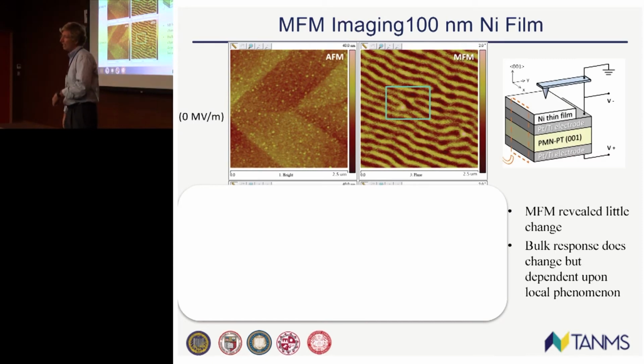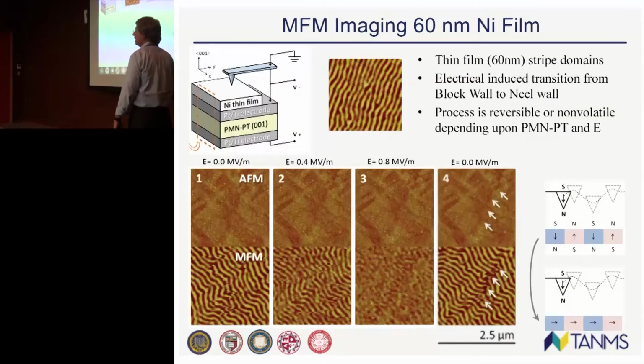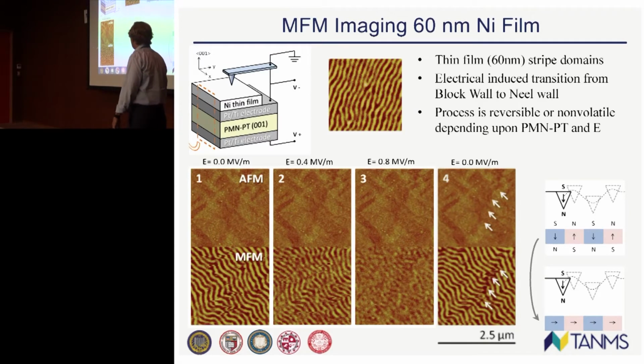So let's do this test again. Now let's do it on a 60 nanometer thick film, not 100 nanometer. You still have these flux paths coming off the surface. You still see you have a striped domain pattern, no different than what you saw on the previous slide. But now let's go in and let's do our test.